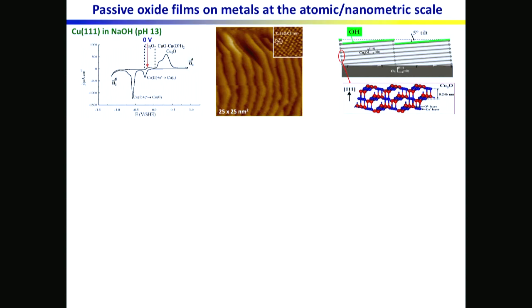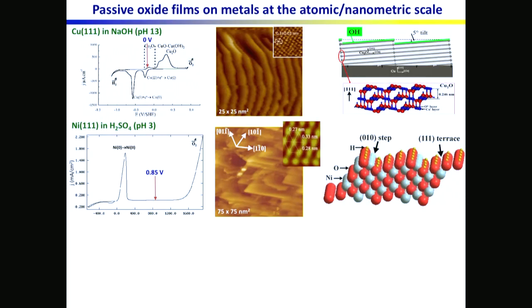The next example is the case of nickel. So this time, we also use the nickel single crystal. So they both crystallize in the same system, the face-centered cubic system. So the starting surface has the same structure. We also use a 111 orientation, but this time we looked at acidic solution.